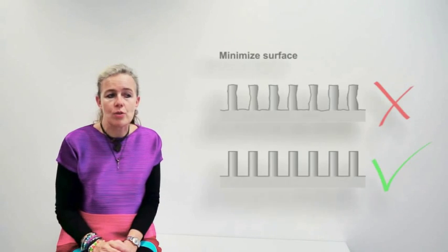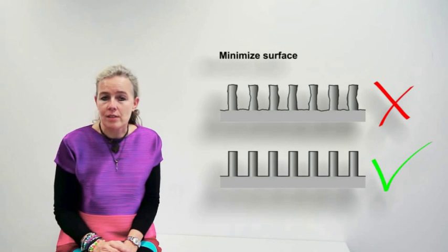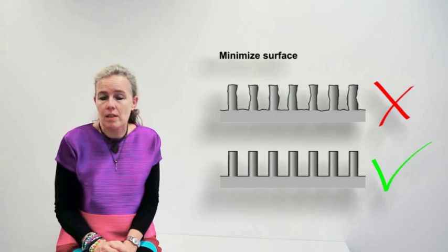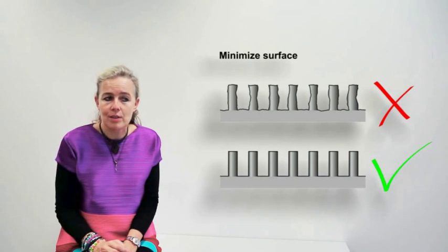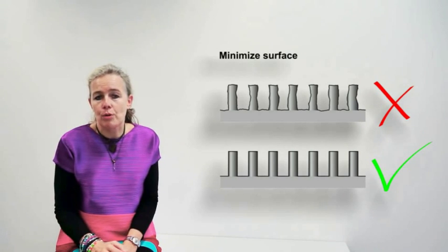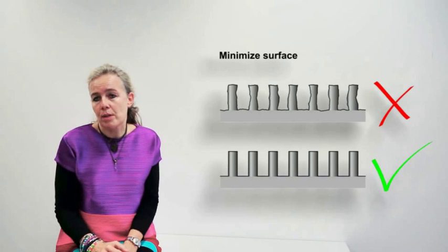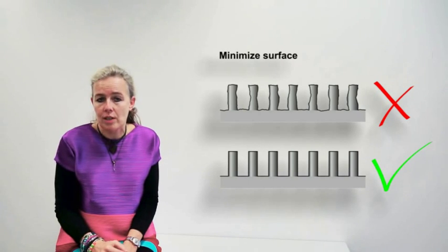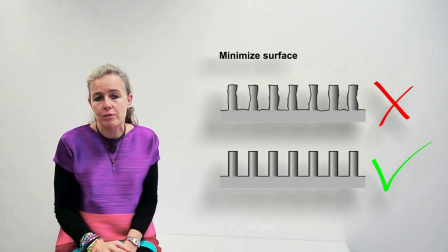You have to tune the diameters, the geometries, the pitch of nanowires, the accuracy of processing. That's one thing. And then also you have to reduce the surface area as much as possible because surfaces are prone to carrier recombination, which are then lost for solar cell or photocurrent for solar cell efficiency.